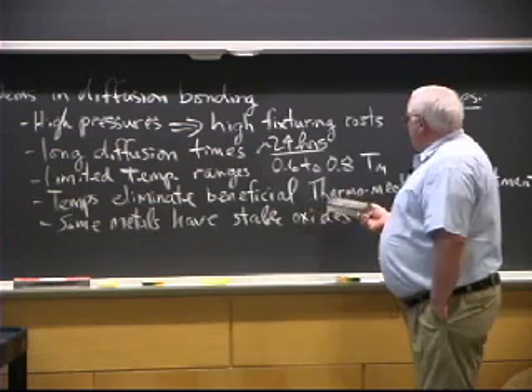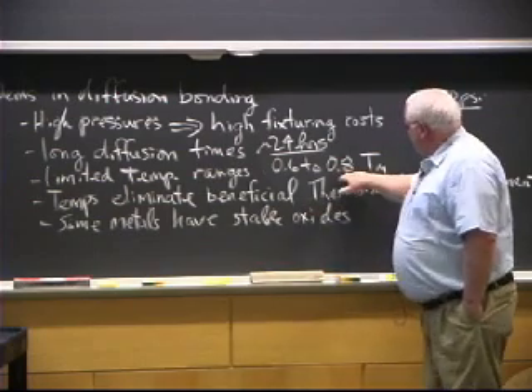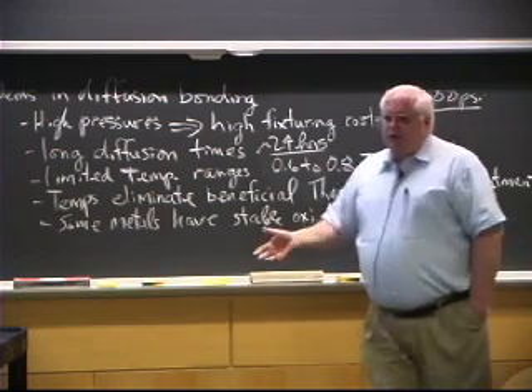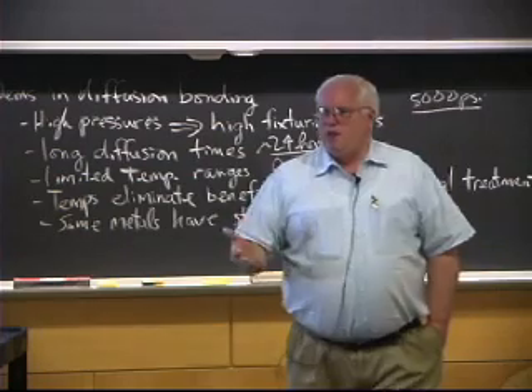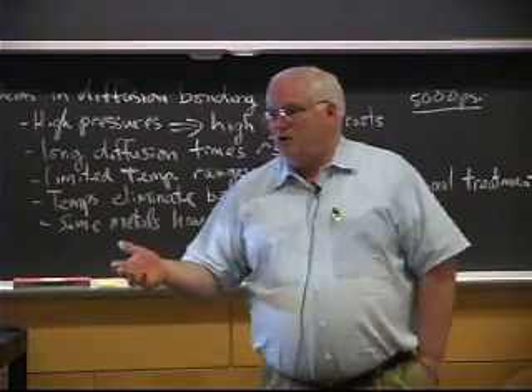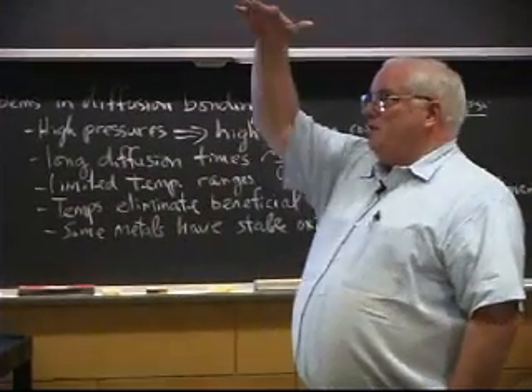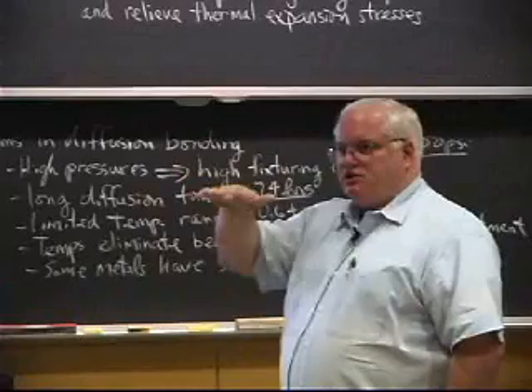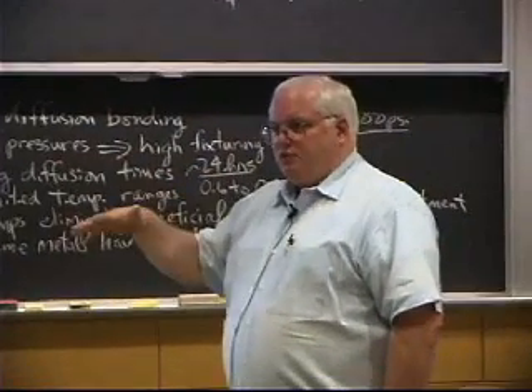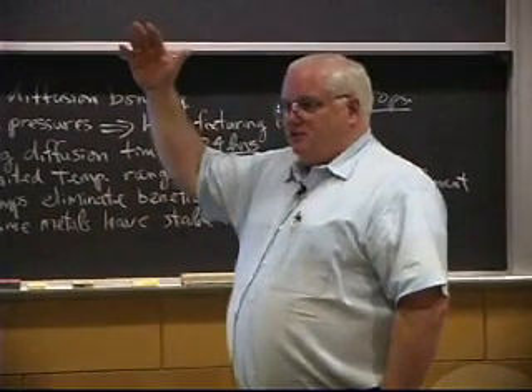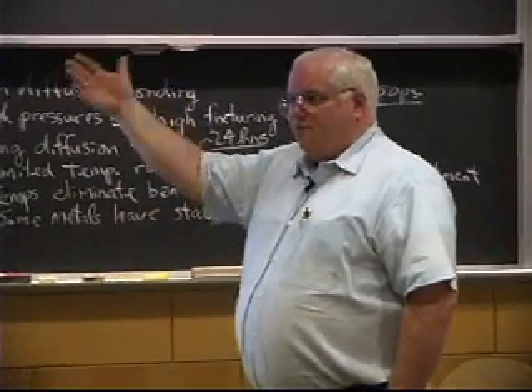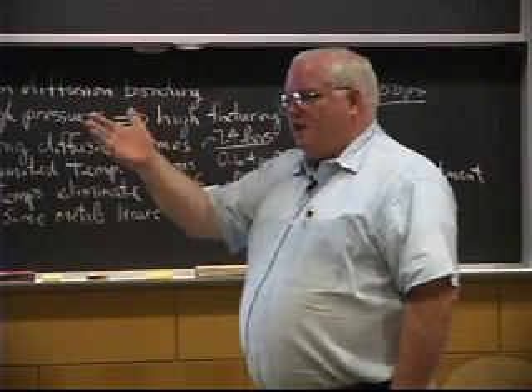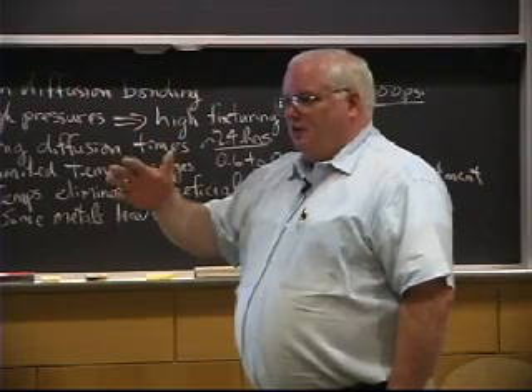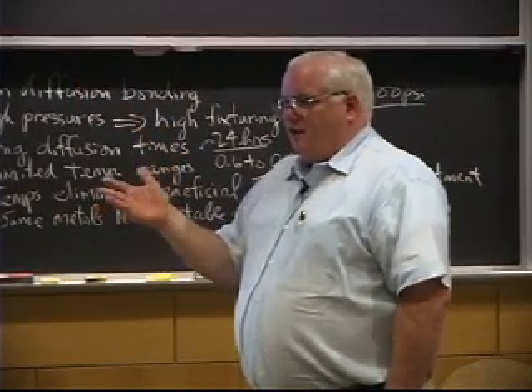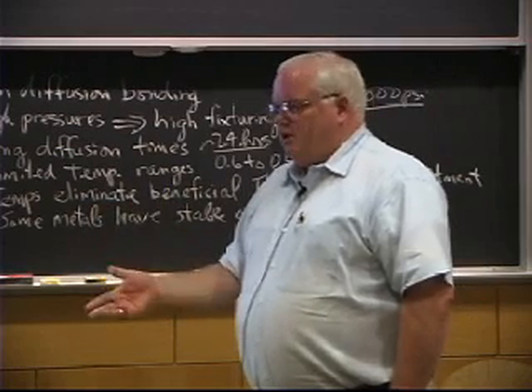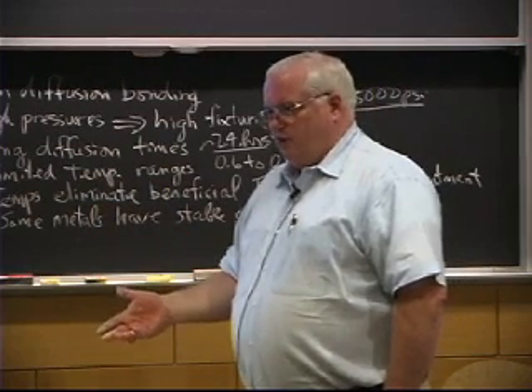The high temperatures that you have to process this at will eliminate any beneficial effects of thermomechanical work. A lot of the high-strength aluminum alloys get their strength because I heated them up, quenched them, solutionized them at a low temperature to get precipitates. If I go above the solutionizing temperature to do the diffusion bonding, I just wiped out all my beneficial effects. HY80 is quenched and tempered steel. I can't diffusion bond HY80. It won't have the properties afterwards. I'm going to have to completely reheat treat it after I do the diffusion bond.